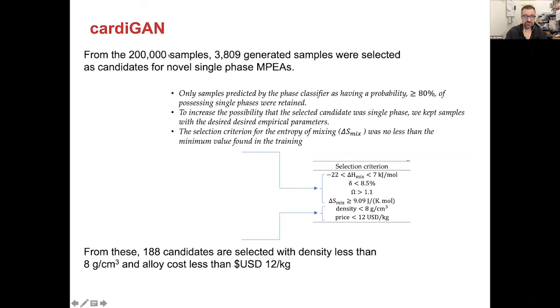It turns out that from 200,000 samples, 3,809 samples were selected as candidates for novel single-phase multi-principal alloying elements. Now, from these, 188 candidates were selected with a density less than 8 grams per cubic centimeter and an alloy cost less than $12 US per kilo, which is really, really interesting.